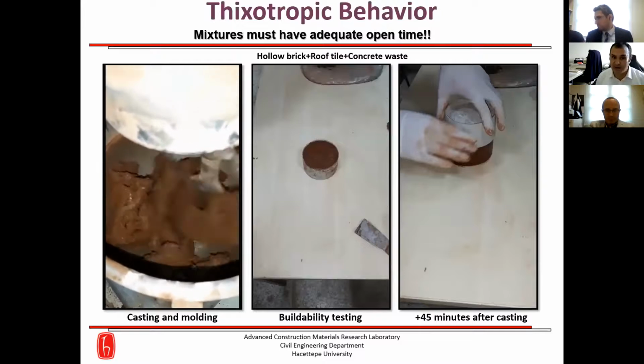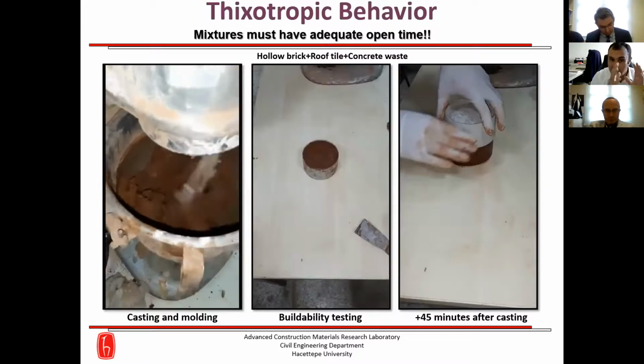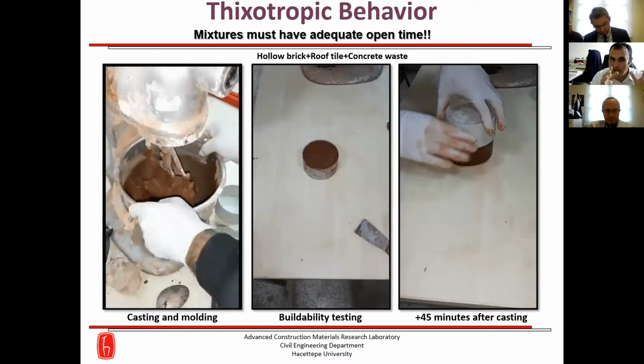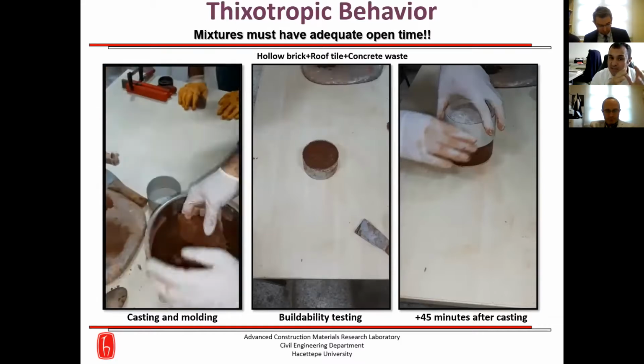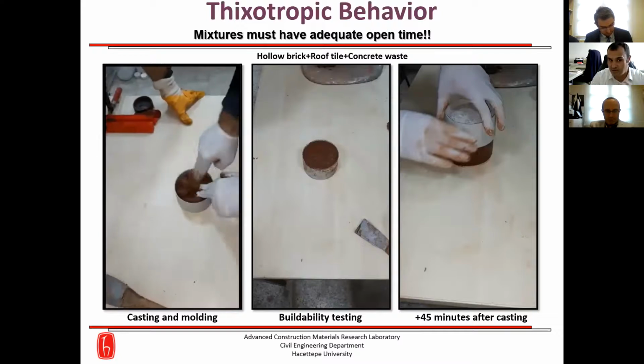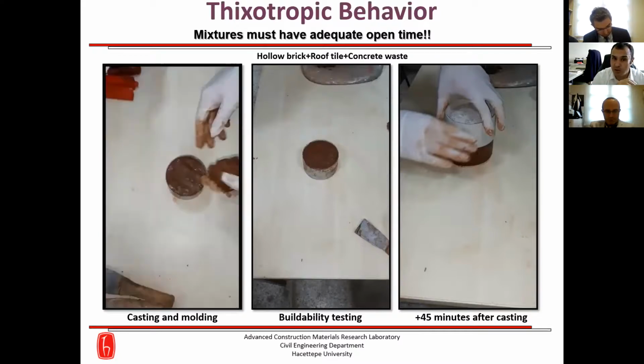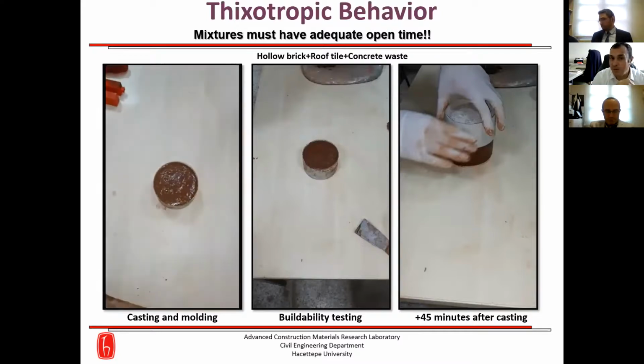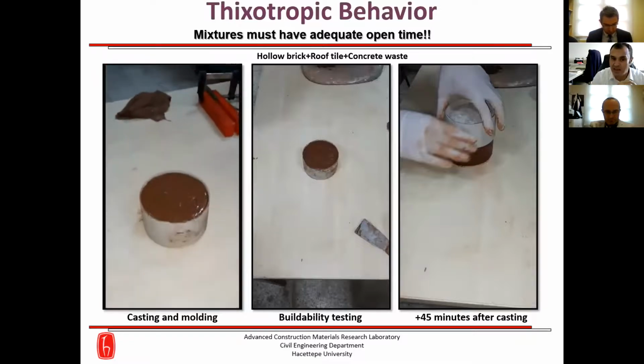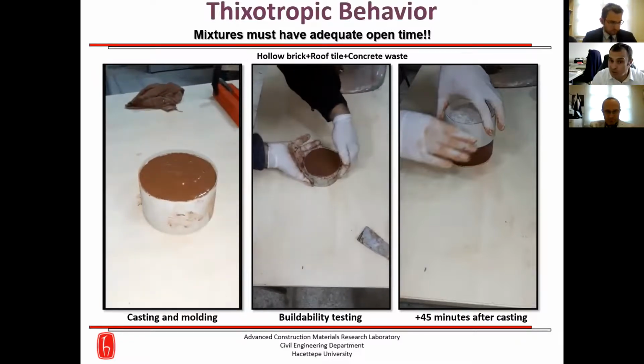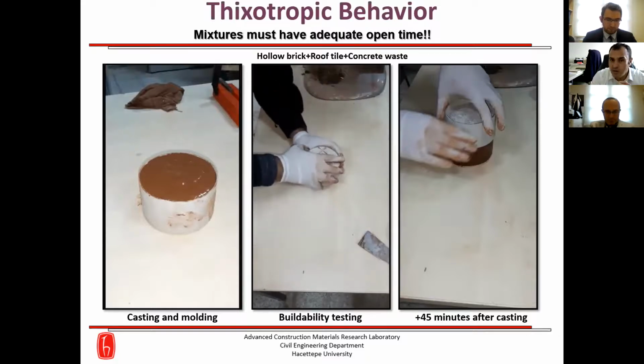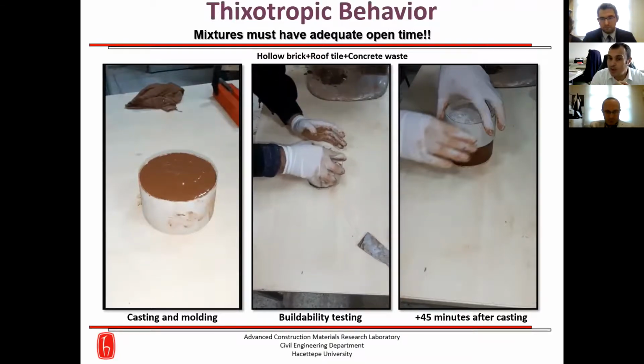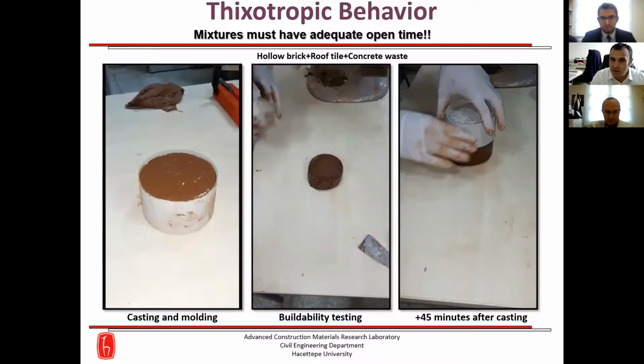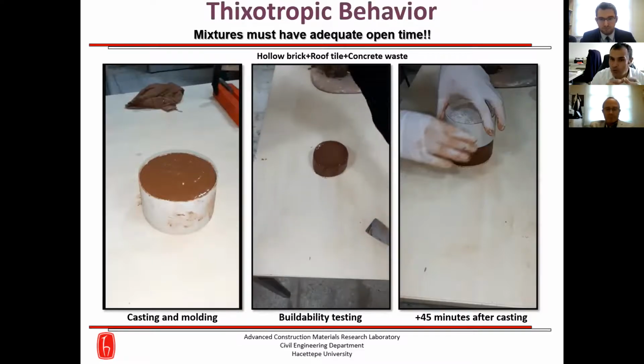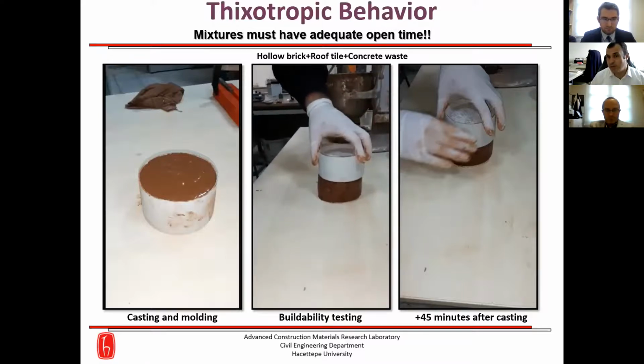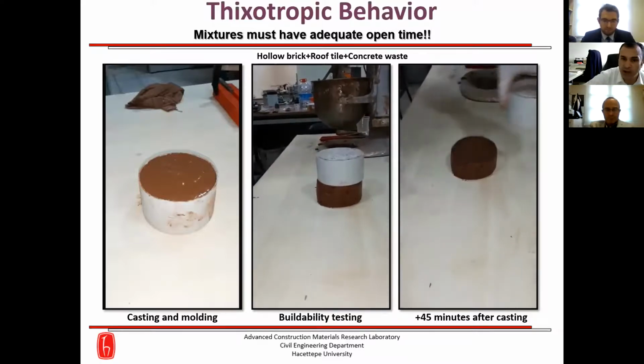Look at this example, a very simple test. We produce the material in the mixer. When the mixing is completed, we obtain the sample from these materials, 100% made from construction and demolition waste. When the sample is prepared, in the second stage, we remove the molds from the specimen and we put some amount of weight over the specimen. When we put the weight over the specimen, the shape of the specimen should remain stable. This is a weight of around 1 kilogram.